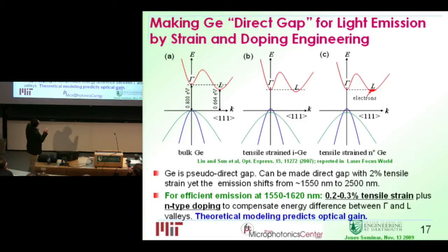So let's talk about light emitters, which is the holy grail for silicon photonics. So how do we make germanium direct gap, as we talked about? We already talked about a trick of using tensile strain, so you already bring these two values closer. Again, think about this as a bowl with two bottoms. So now you want to fill electrons inside, but still, because this is lower, you fill electrons first into this valley, and after you fill quite a lot, you can go to this valley.